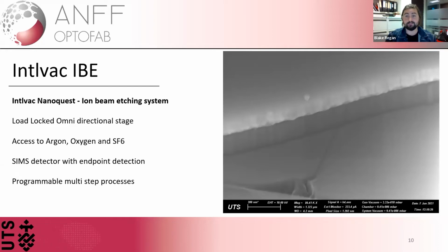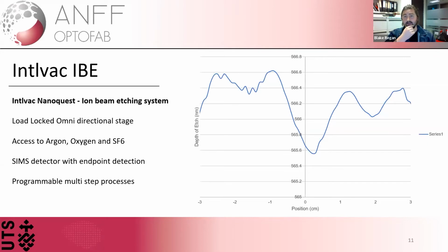as you need. In terms of repeatability, I've included in here some of our initial testing when we were determining the roughness of the etch over a wide scale. This is a silicon dioxide substrate, and as you can see, over the area of 6 centimeters, centering on the middle, this is all done with ellipsometry measurement. We found that the roughness of the etch across the substrate was only 1 nanometer or ½ nanometer plus minus. So in terms of etching accuracy, I was personally quite impressed by it, but I'd like to be able to impart that etching quality off to you guys as well.